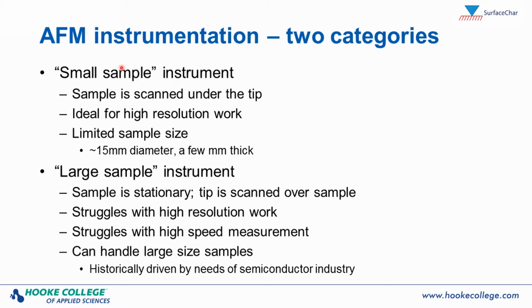There are what we refer to as small sample instruments, where the sample is what is moved and scanned under the tip. This is really the kind of instrument you want for the high resolution work, like atomic scale work. The problem is that it comes with a very limited sample size, because the sample is being moved tiny amounts, 15, 20 nanometers, so you can't have a large mass being moved around.